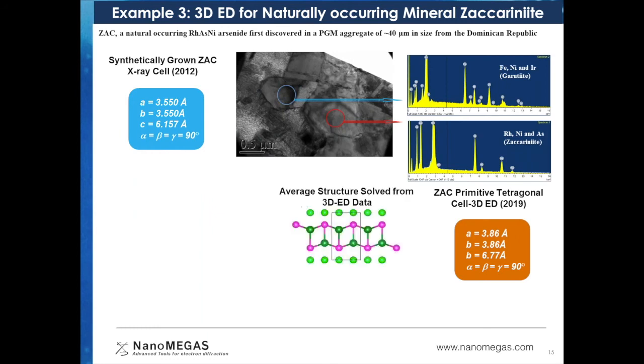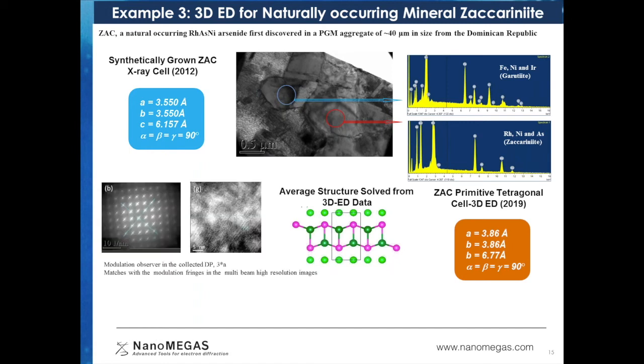And this result obtained from the naturally occurring mineral matches very closely with the result obtained from the single crystal X-ray diffraction data. But we had some additional observations. We saw the presence of modulations in the diffraction pattern, which we also confirmed by looking at the high resolution images of this material, which was not reported and not observed in the synthetically grown material of this mineral.